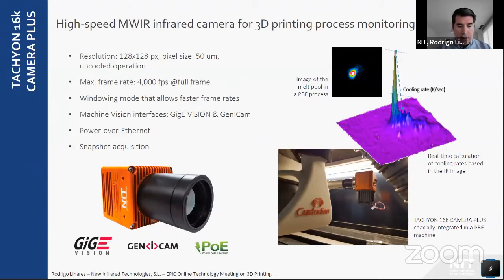And one 3D printing method that can benefit directly from these features is the powder bed fusion process, which is very dynamic and requires very high frame rates. Here on the right, you can see the camera coaxially integrated in a PBF machine. Here also the image of the melt pool taken during the process. This image can be analyzed to take relevant information like dimensional information and infrared intensity during the process, and study the relationship, for example, with the movement of the scanner or the applied power. Or, for example, study the instantaneous cooling rate in real time.